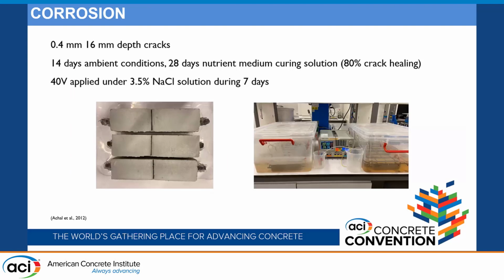Corrosion. We cast the samples, both including bacteria and without bacteria. We created cracks 0.4 millimeters wide and 16 millimeters deep by using steel plates. And then after casting, we left the samples 14 days in moist condition. Then after the 14 days, we put our samples containing bacteria submerged in the nutrient medium for 28 days. When we observed 80% crack healing, we put our samples into our corrosion setup.